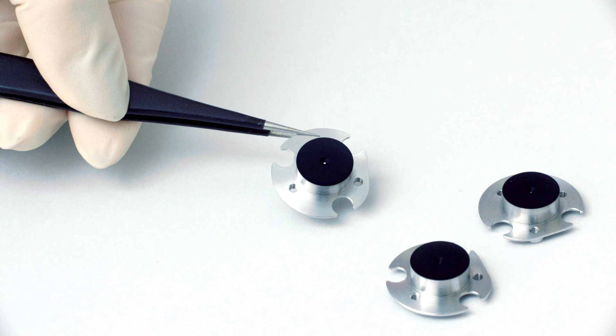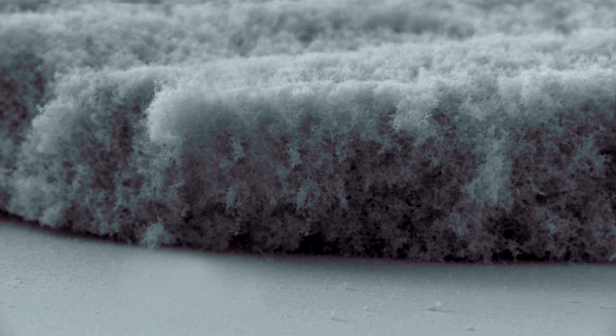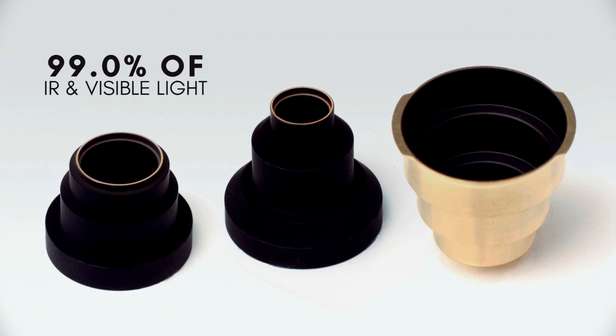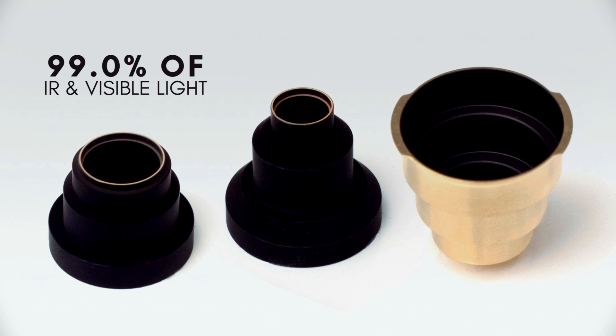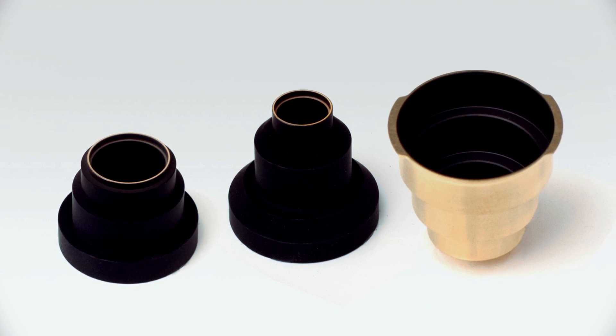Moving beyond the absorption abilities of pigments would require coatings to take on microscopic structures in order to better trap light. Gold black was one of the first commonly used light-absorbing nanostructures, created by high-pressure inert gas deposition of gold onto a substrate. This causes the gold to form a nano-chain structure. These chains overlap one another, joining together very loosely, resulting in a fluffy, porous structure that traps light. Gold black can absorb almost 99% of the light that falls on it, and also performs well in the near-infrared and infrared parts of the spectrum, making it an ideal candidate for improving the sensitivity of uncooled infrared sensors.